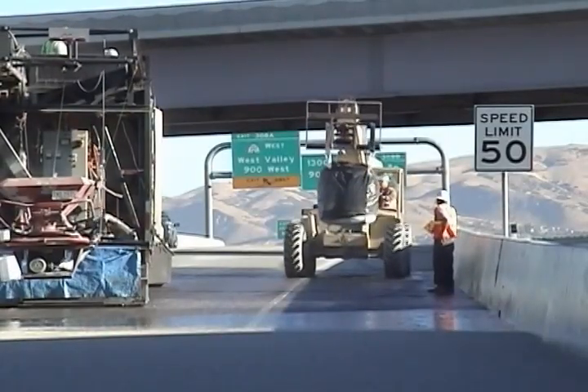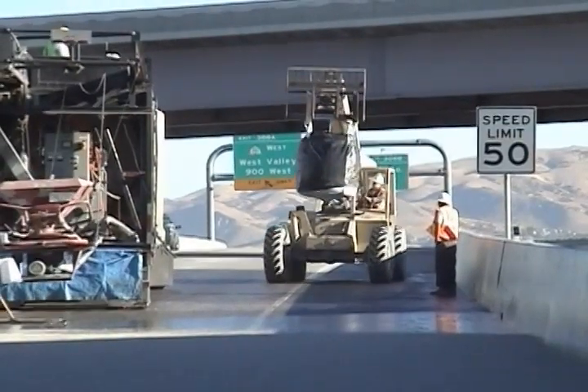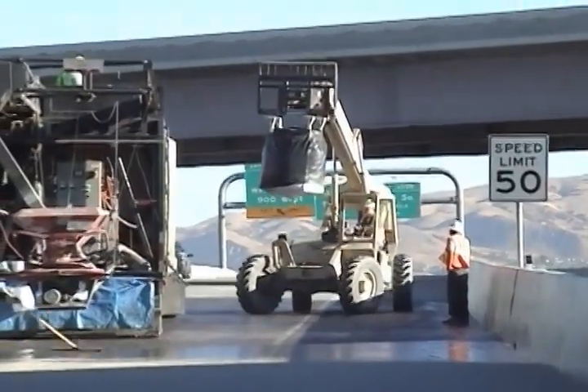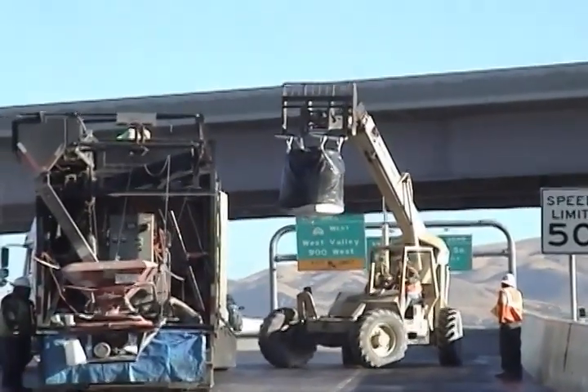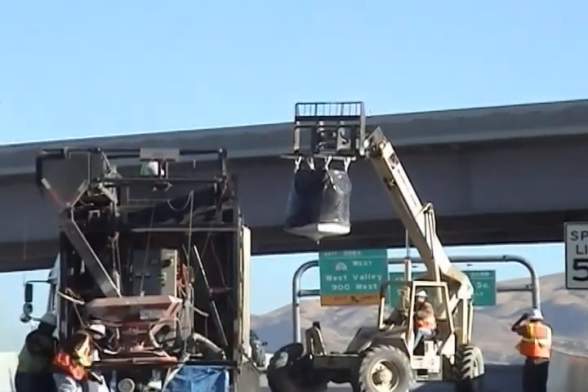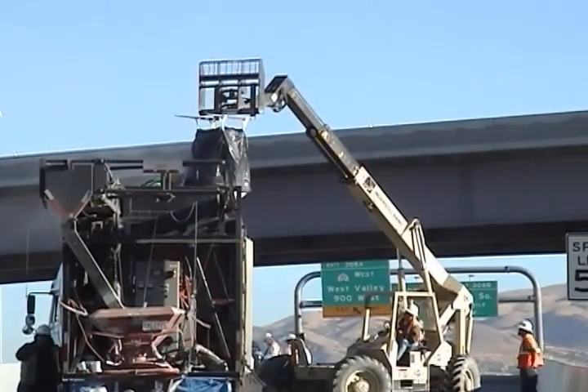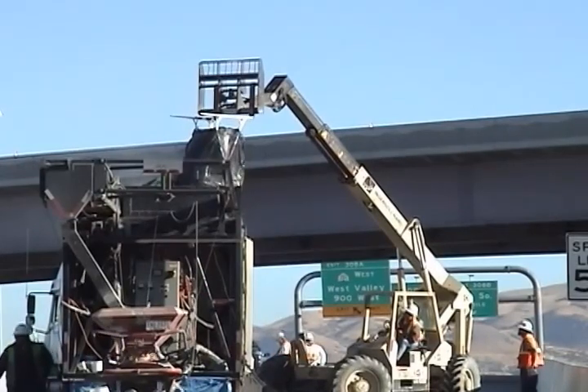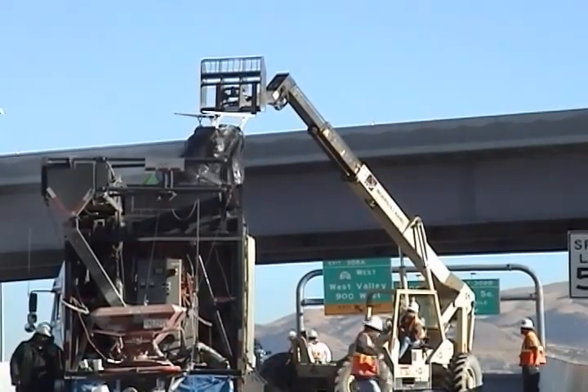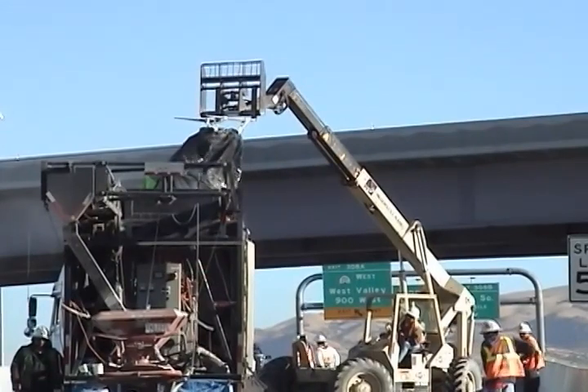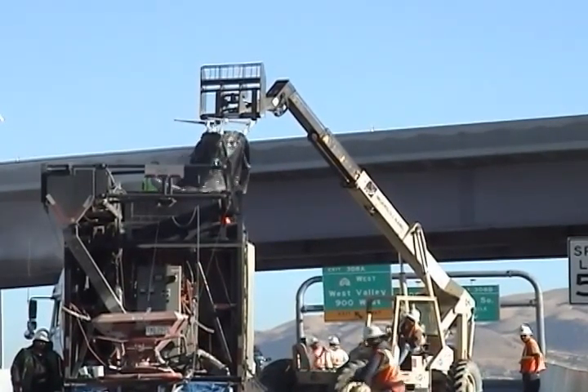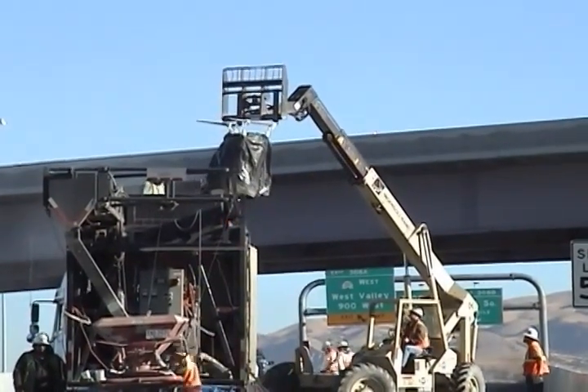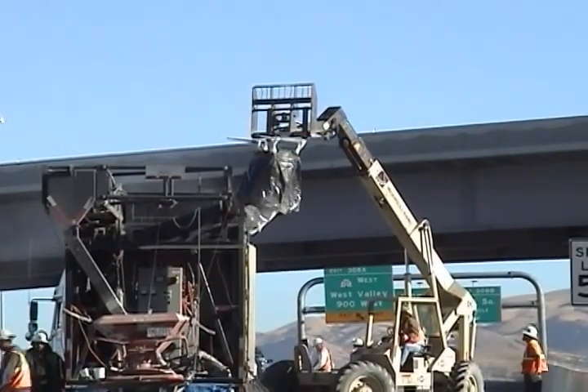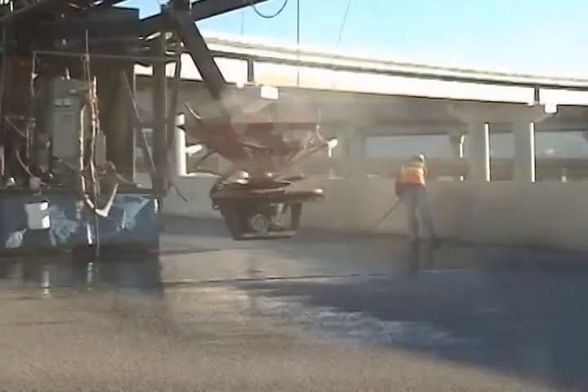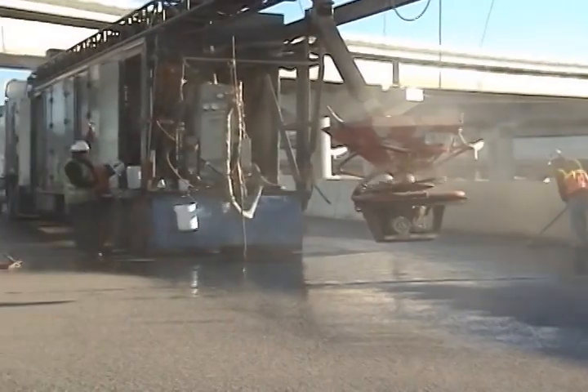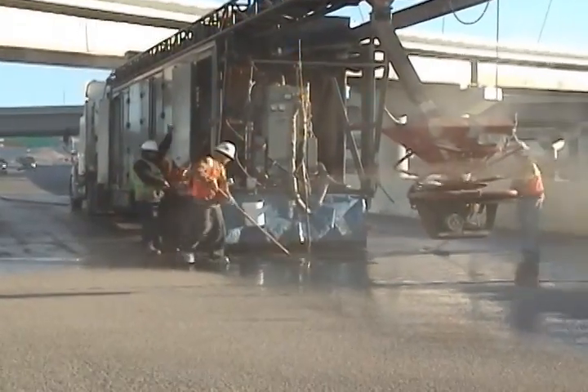Another benefit of using a trailer to carry materials is that reloading the trailer with aggregate is a fairly quick process. The aggregate is loaded into the trailer using a large forklift. Using the Polycarb wagon, 100,000 square feet of overlay can be applied to the deck, cure, and be open to traffic in less than 48 hours, and can be expected to last in the neighborhood of 15 years with minimal maintenance. Mr. Wells also explained that in his experience, other overlay systems involving waterproofing rubberized membranes under a layer of asphalt can be expected to fail after 2 to 3 years of use.